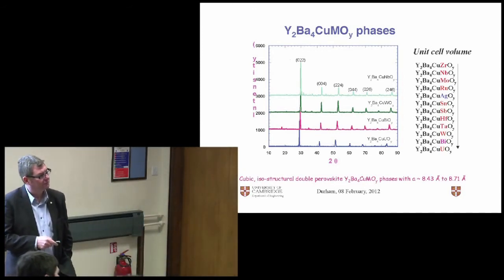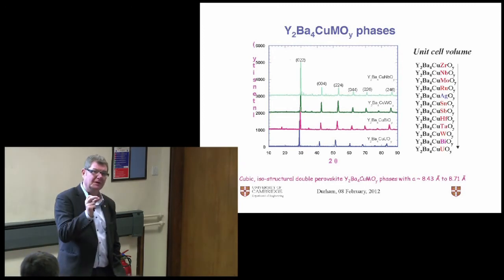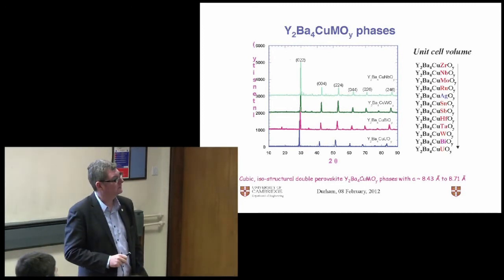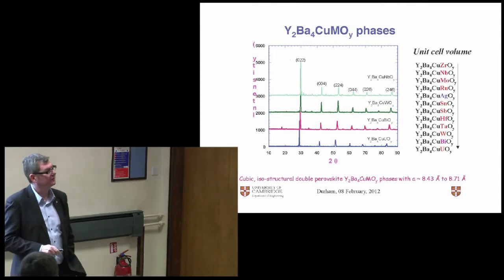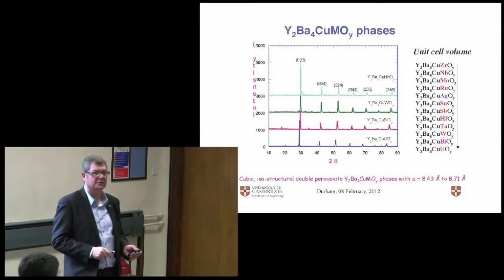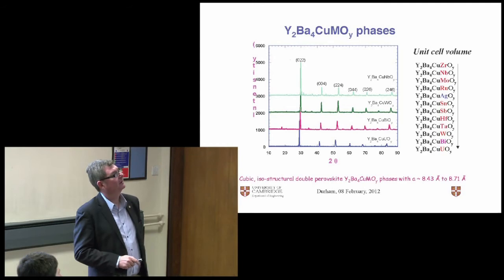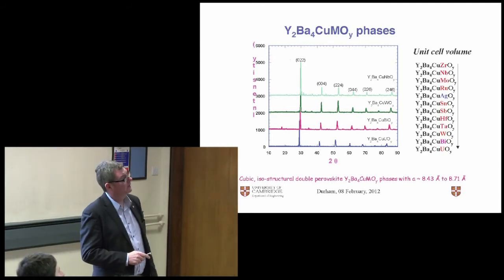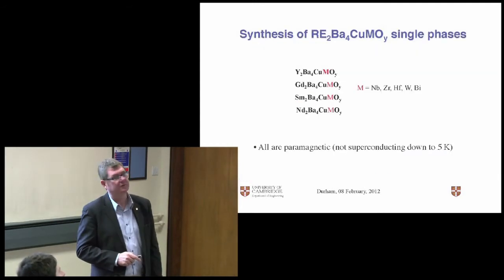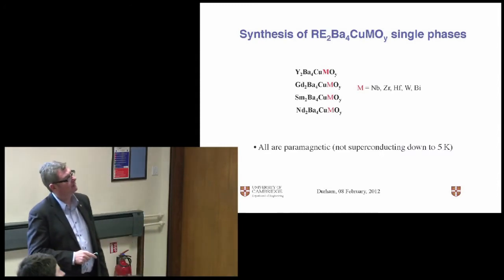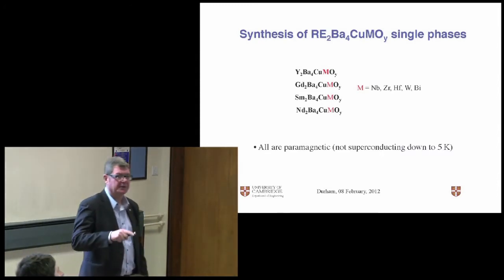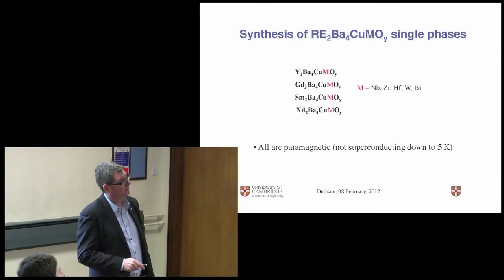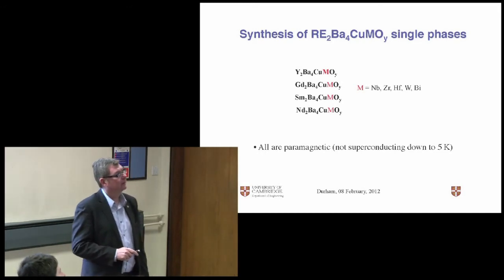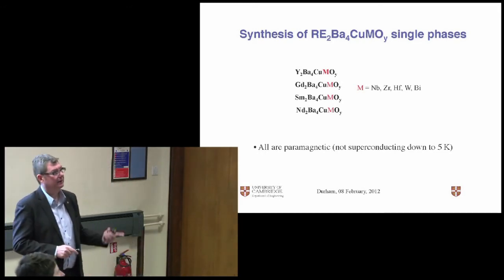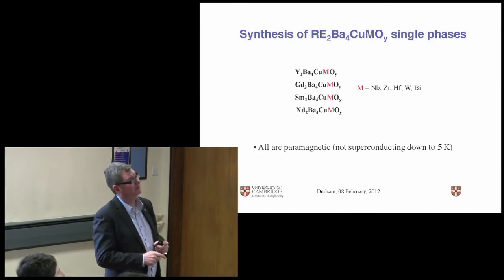So we then decided to work out what this phase was, but typically it's 40 to 50 nanometers in diameter. It's so difficult to identify the phase composition, and it took a long time to do it. But when we did, what emerged was a new phase. We call it the 2411 phase: yttrium 2, barium 4, copper 1 and something else. In that case, the something else was uranium. So it's a 2411 where the 1 is uranium. I guess that took 2 years to identify that phase.